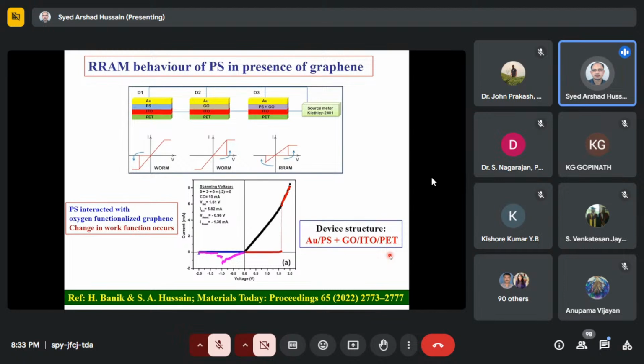Then we mix this polystyrene with graphene and found that initially polystyrene was showing write once, read many, ROM kind of behavior. But when it's mixed with graphene, we have seen that it shows bipolar switching. That means RRAM kind of behavior. Here mainly the work function of our active layer material polystyrene is affected due to the presence of graphene, so conduction is also affected. So it shows bipolar switching.